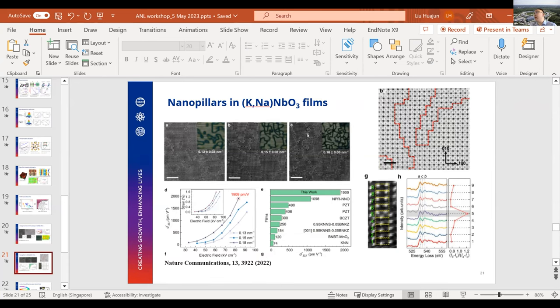So this nanocomposite way, forming this kind of pillar, may be a little bit limited to the niobate system, but forming this kind of self-assembled nanocomposite is quite often seen. I think a few different groups already tried a similar idea with lead titanium oxide and barium titanium oxide, but they're not the anti-site way. They're just using the primary oxide, like lead oxide or barium oxide, forming another phase as an intrusion. That also enhances the d33 coefficient a lot. But the nanopillar, like the one Huajun showed, is right now probably more unique to niobate-based systems.